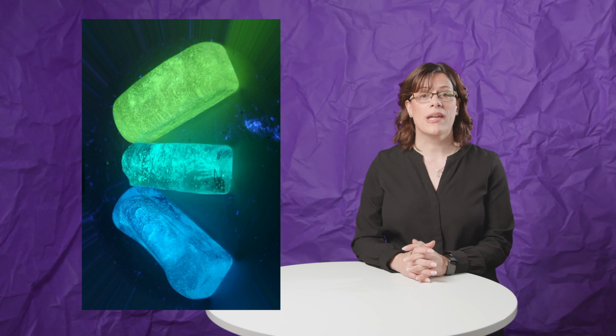Using this technique, we prepared new glass-based composites with persistent luminescence, for example. Persistent luminescence refers to the type of emission which lasts for a long time after the removal of the irradiation source. The persistent luminescence was obtained by adding persistent luminescent crystal in the glass. These composites could find application in bioimaging, for example.